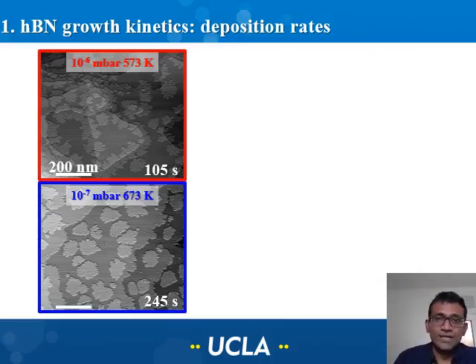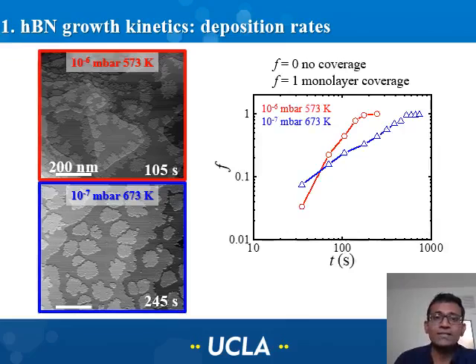Okay. Based on these time-lapse images, we can now extract quantitative information on the growth mode and the growth kinetics. As a first step, we calculated the coverage of hexagonal boron nitride as a function of deposition time. I'm going to showcase only these two particular cases because these give the extreme deposition modes. In this plot, F is the coverage of hexagonal boron nitride on palladium-111. If it's 0, it means clean palladium. If it's 1, it implies complete hexagonal boron nitride monolayer formation on palladium-111. The blue and the red curves correspond to the two different growth parameters that we have used in this particular set of experiments.